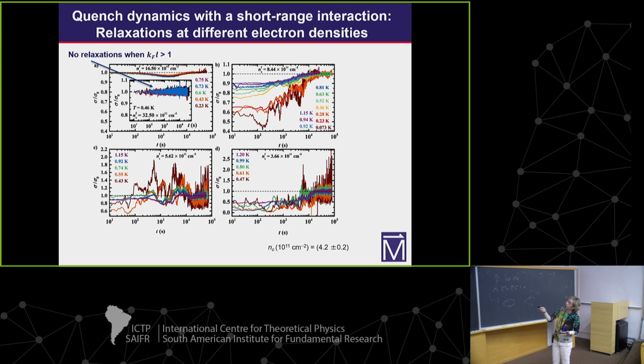This is the result of the protocol performed for higher densities. We do not see anything. Then we reduce the density, when KFL is of the order of 1, we start seeing some deviations.